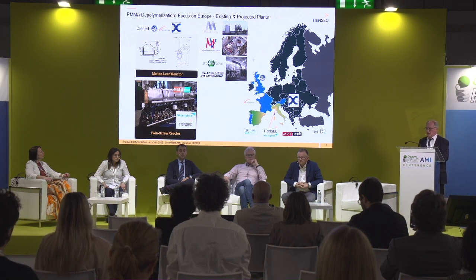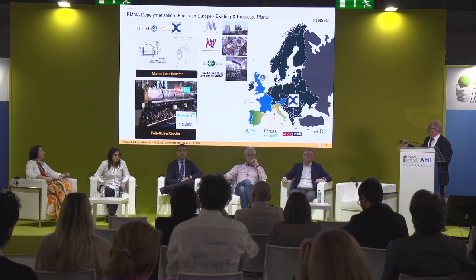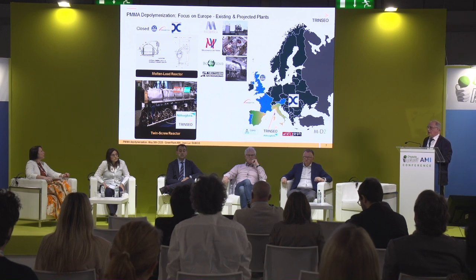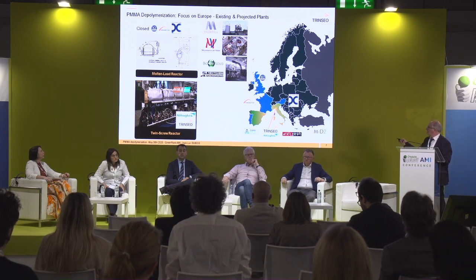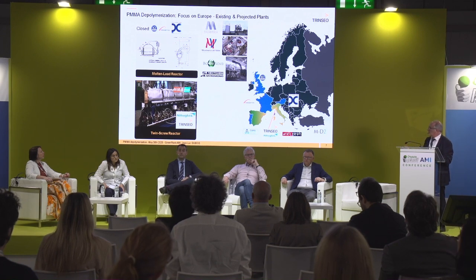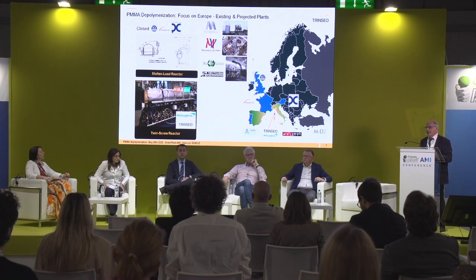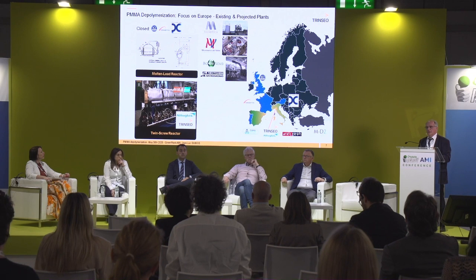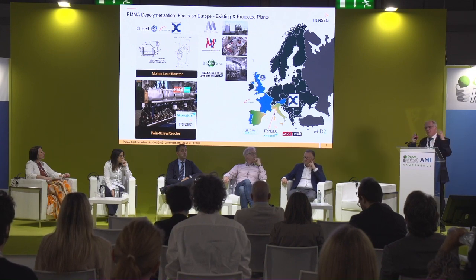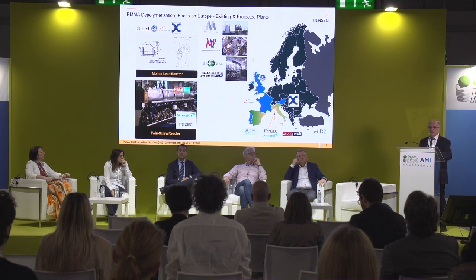There were many plants in the past in Europe. ICI had a plant in UK. Arkema had a plant in France. Evonik had a plant in Austria, Parachemie, which is closed. Those plants are closed. There were also plants in Portugal, in Spain, and so on. A lot of plants have been closed. They were all using the so-called molten lead bath technology. So you have molten metal at high temperature, 400 degrees C and more, and you pour the PMMA into this molten metal bath, and there is heat transfer, and then the polymer depolymerizes.